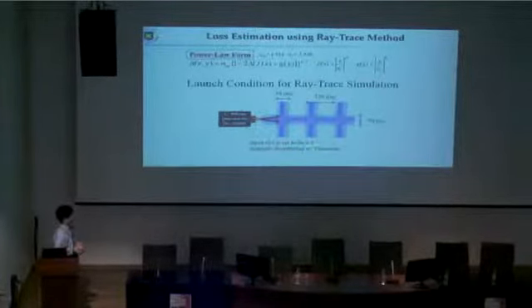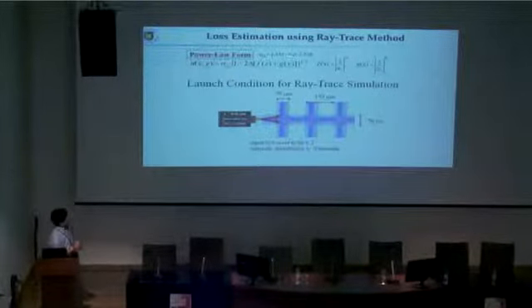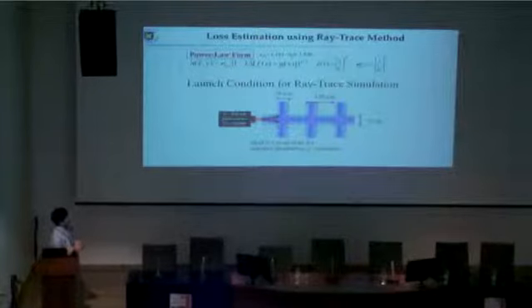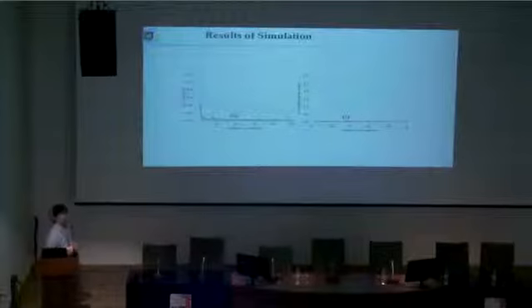So we simulated the crossing loss in graded index and step index cores using ray tracing simulation. Here is the condition for the waveguide and the index profile for the core in horizontal direction and vertical direction. And here is the calculated result. This is just a simulated result. With increasing crossing number, the loss per crossing in the SI waveguide decreases, because at the initial stage, higher order modes frequently colliding with the cladding are leaked out. And then there is a small possibility of leaking out at the intersections in the case of the SI waveguide.